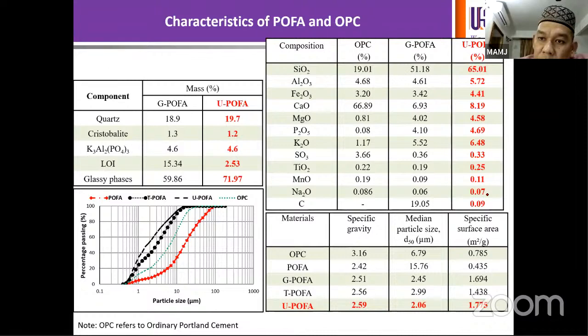So as a result of this reduction in carbon content and increase in the pozzolanic oxides, that turned the material into a very efficient pozzolanic material. Further analysis, comparing the G-POFA and U-POFA, shows a significant increase in the glassy phases from about 60% to more than 70%. So this is the amorphous content within the material.